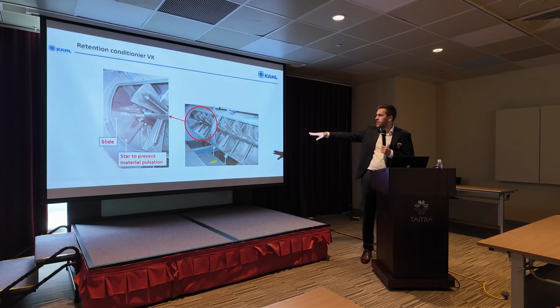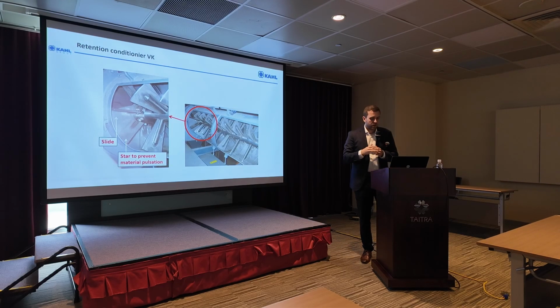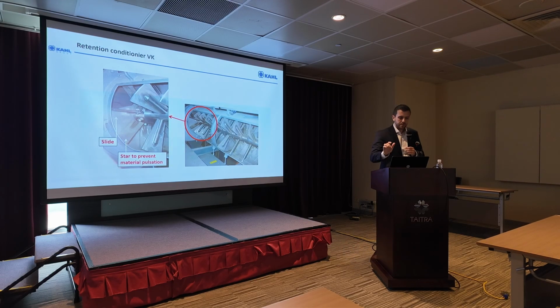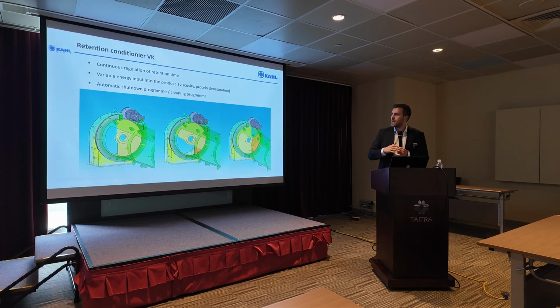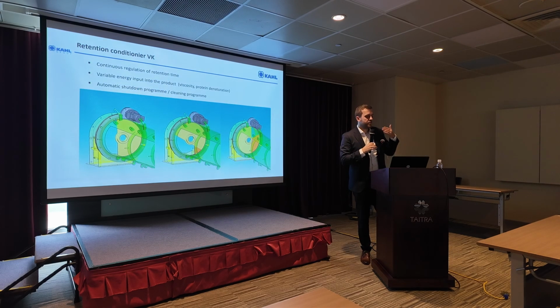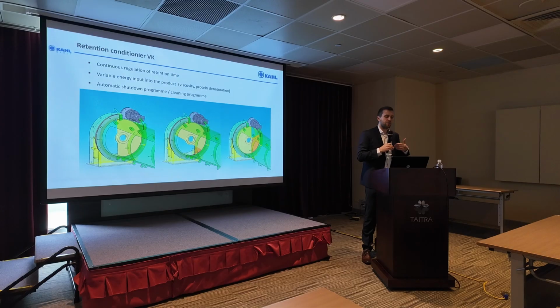At the end of this retention conditioner, we also have a special slide. I will show you on the next slide here. Because this actually allows to decrease and increase the flow rate through the conditioner into the extruder. With this slide, we are able to open it or close it, and depending on that, we have the material flowing back into the conditioner, allowing a longer retention time.